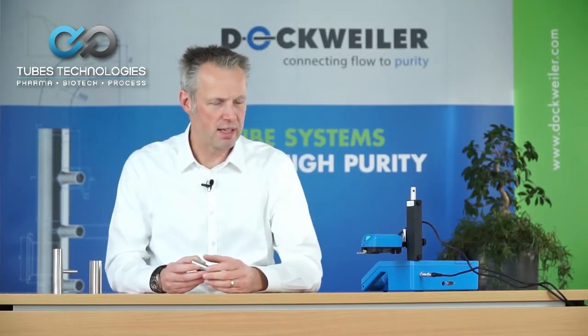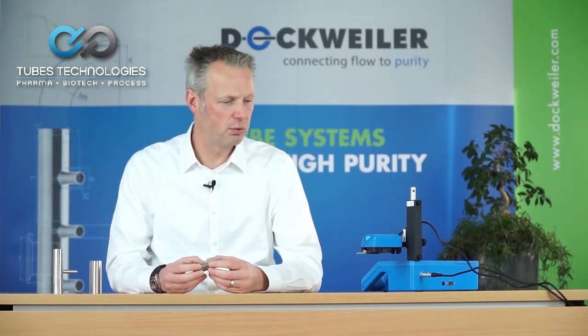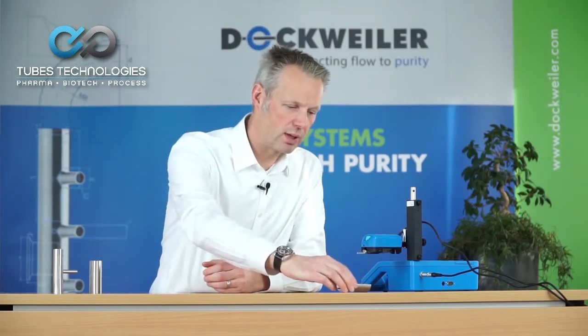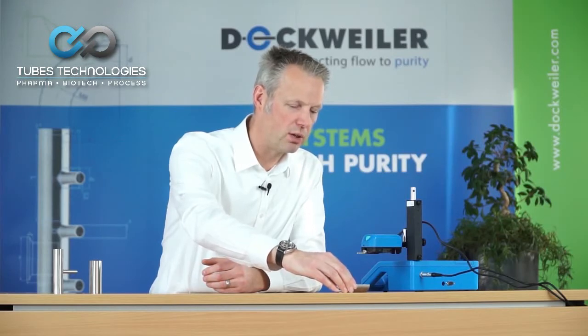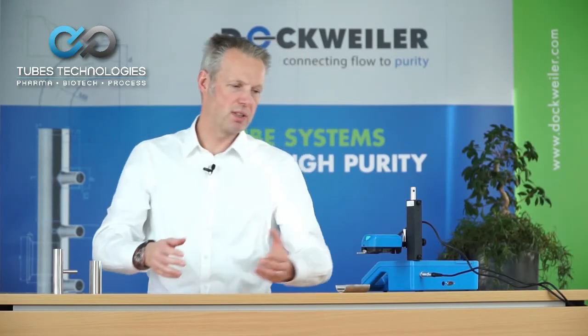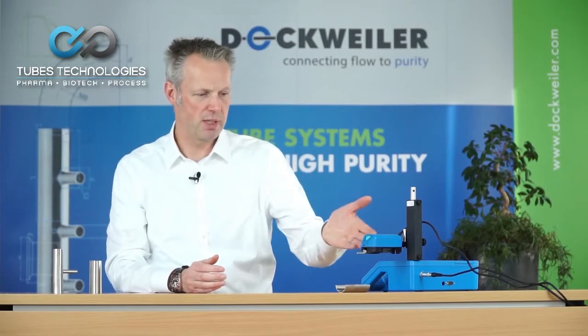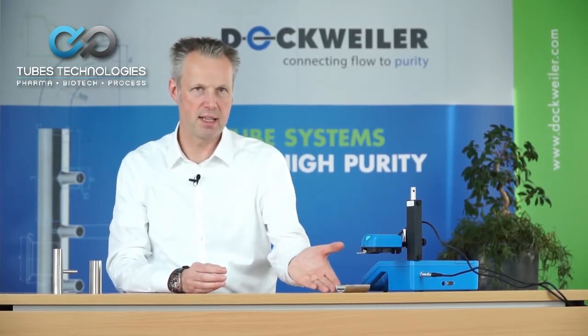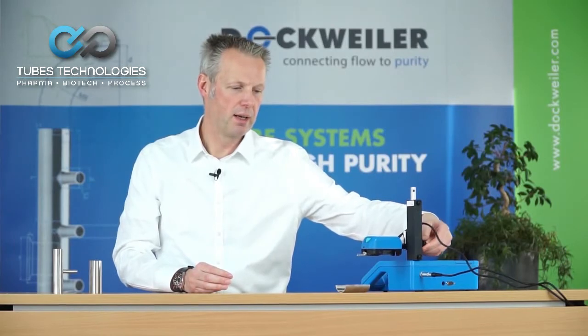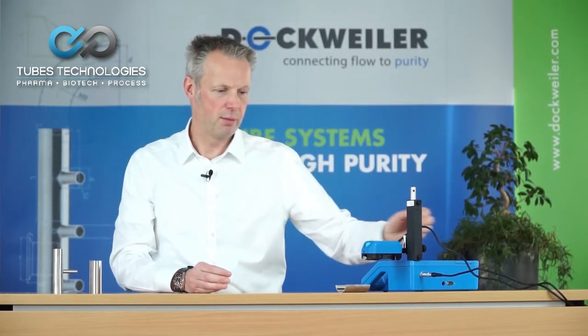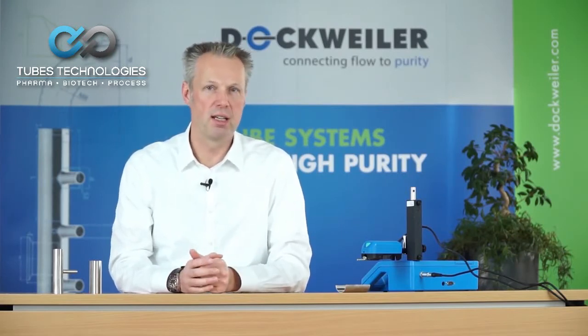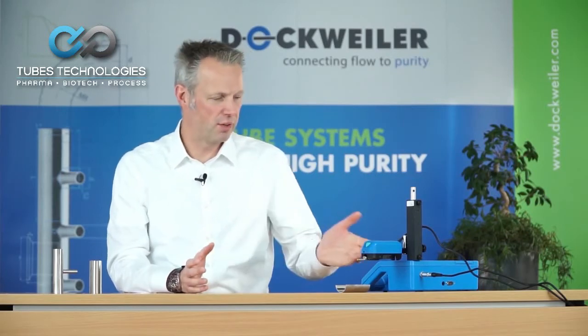I brought you here a standard measurement device for an RA value. With this one you can determine the topography of a surface. It works in this way: you have a measurement head like this. You place a sample underneath and you can then lower the measurement head so that the diamond tip, which is in front, is touching the surface, which is at the end of the day self-aligning. So this device also gives you some aid with regard to the adjustment.